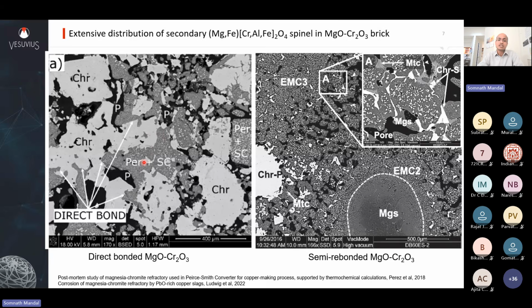And all of this generates a very high temperature resistant, highly corrosion resistant bond, which makes these materials so highly performing. This is a more improved version, semi-rebonded magnesia-chrome. Here they use pre-fused magnesia-chrome aggregates as raw materials. You see these bright chrome-rich regions, and then you have the magnesia matrix. A blown-up portion is here. So these are secondary chromite precipitated inside the periclase or magnesia grains.